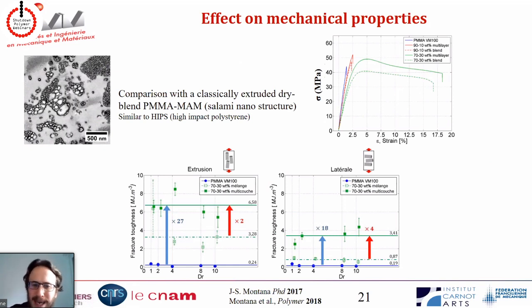And if we now look at the mechanical properties of these multi-layer films and compare them with blends, classical blends, where we just mix the two materials together, and in which we can see this really typical salami nanostructure, we can see that the mechanical properties of both blends and multi-layers are better than virgin PMMA in blue, which means that we have a really large increase in the elongation at break, so the impact properties are enhanced. But what we can see also is that the multi-layer films have better properties in terms of fracture energy than the blends. So by controlling the architecture, by creating one more level of architecture, this multi-layer structure, we can reach better properties than blends where we just control the phase separation of the copolymer.